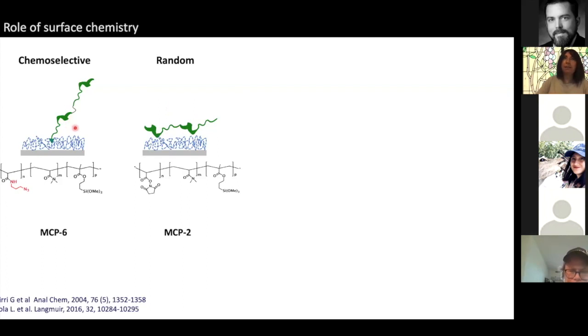When we move to peptides that are very small, very tiny molecules, it is important to have a chemoselective immobilization. So that's why we use this MCP6, which is a derivative of MCP2. The components of the polymer are exactly the same except for the functional monomer here that is not an NAS, it bears an azido group, which, as I mentioned before, is able to react chemoselectively only with the bioorthogonal group, that is the propargyl glycine in the peptide that we spot on the surface, in such a way that we are sure that the peptide is immobilized in an oriented way and is also spaced from the surface due to the linkers that we add during the synthesis. And the difference between these 2 surfaces, even if just a minor component change, is dramatic.